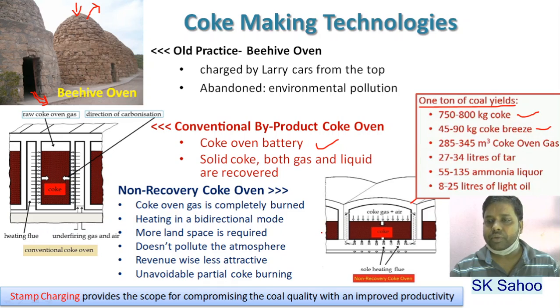In non-recovery coke oven plants, the coke oven gas is completely burnt inside the chamber. Heating is in bidirectional mode, whereas in the conventional byproduct coke oven it was lateral heating. Here the heat goes from both directions, from top to bottom. More land space is required as the height of the bed we cannot increase much, but it doesn't pollute the atmosphere because it doesn't go for any byproduct recovery plant, or all the byproducts are burned inside the coke oven. So it also leads to less revenue generation. That means revenue wise it is less attractive,